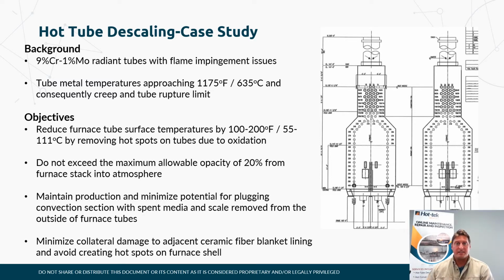But again, what I'm saying about the scale or the oxidation not being able to be cooled by the process, once we remove that, we can see tube surface temperatures reduced by 100 to 200 degrees Fahrenheit, depending on how long it's operating and how heavy that scale is. We also try not to, again, since we're not introducing too much foreign media, the impact that we have on the heater itself is very minimal, but we also keep in constant radio communication with operations.